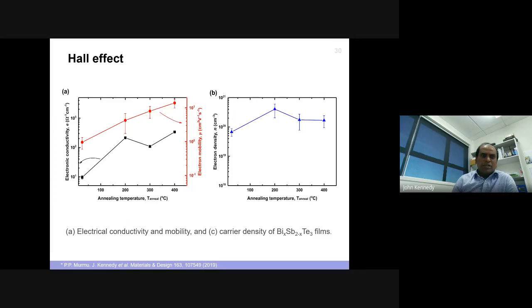What we produce is contrary to the P-type material reported in the literature, because we deliberately made an understoichiometric film. It's tellurium rich in the as-deposited films, which gives the N-type behavior. So that's the difference from the previous results.